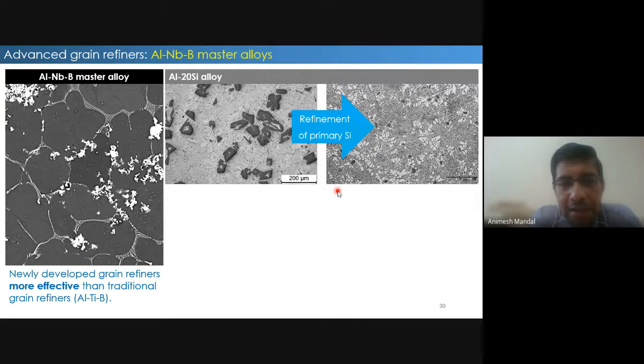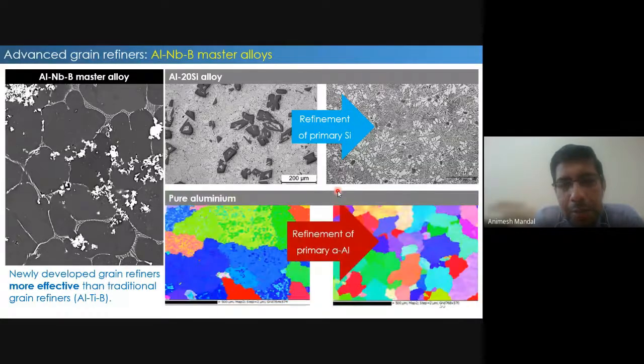For example, it has been tried out in certain hypereutectic aluminum silicon alloys, and you could see that you can not only grain refine the alpha aluminum, but also the primary silicon using this particular master alloy. Not only that, even if you take pure aluminum, you can grain refine this pure aluminum, so refinement of primary aluminum is also possible using this. That means simultaneously you can grain refine the primary aluminum as well as the primary silicon. So there are certain advantages of this aluminum niobium boron master alloy over aluminum titanium boron master alloys.